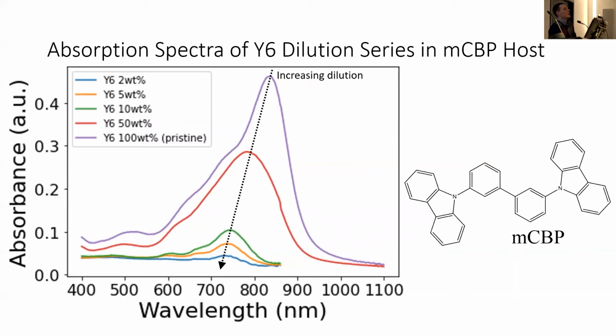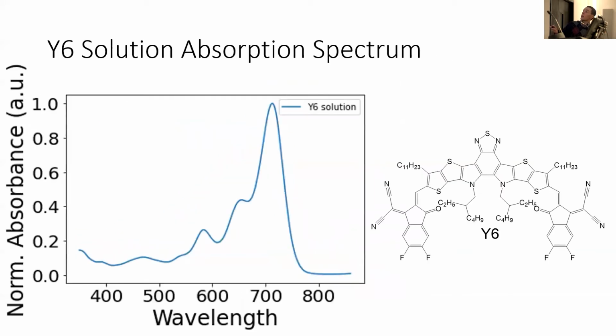So I think the classical Kasha model of H and J aggregates, which I alluded to, is perhaps a bit deficient when looking at these molecules because of the nature of them, an acceptor-donor-acceptor structure with quite a strong quadrupole moment. And then there's a whole extra level of theory about thinking about the aggregates of things with quadrupole moments. I think the short answer to your question is that by the molecules aggregating together, you wash out the effects of the intramolecular modes, basically.